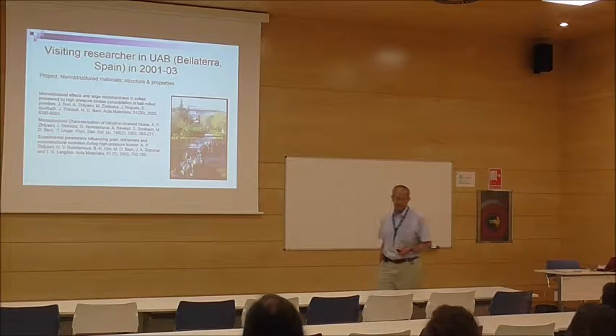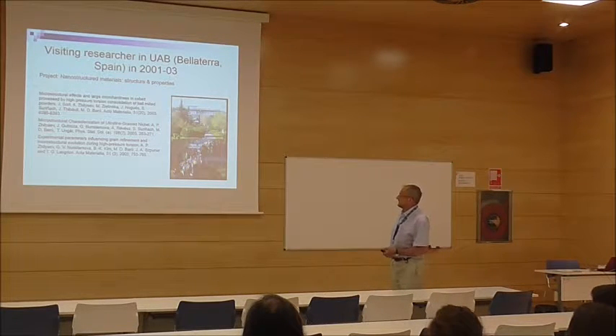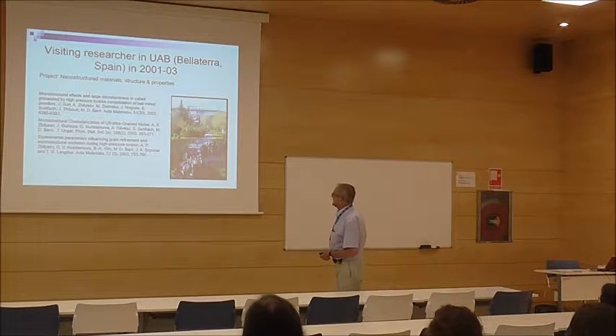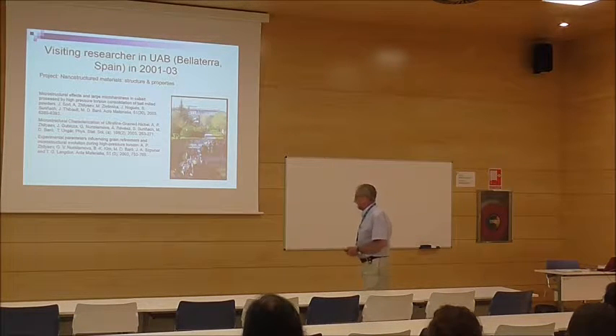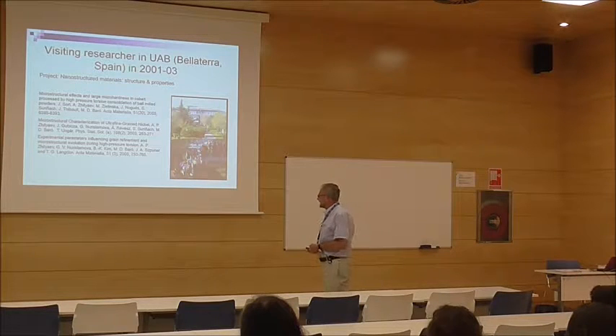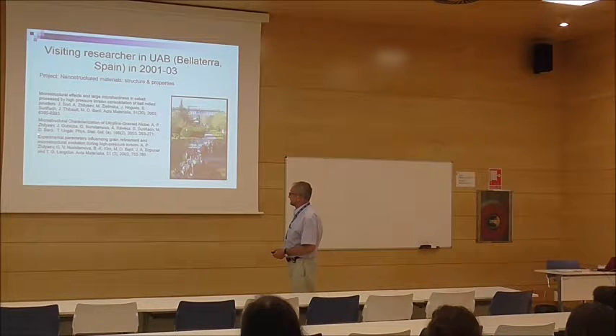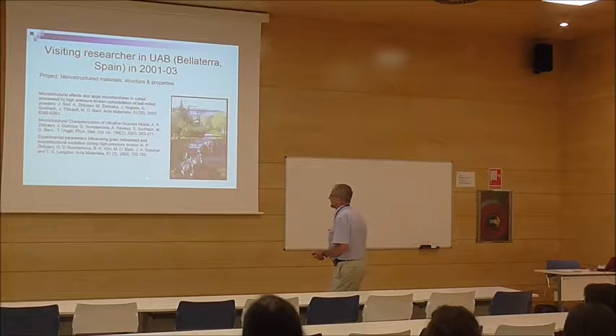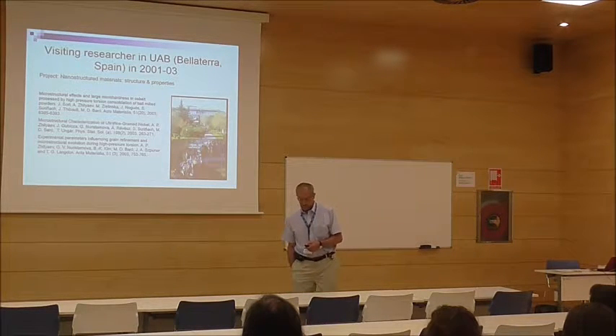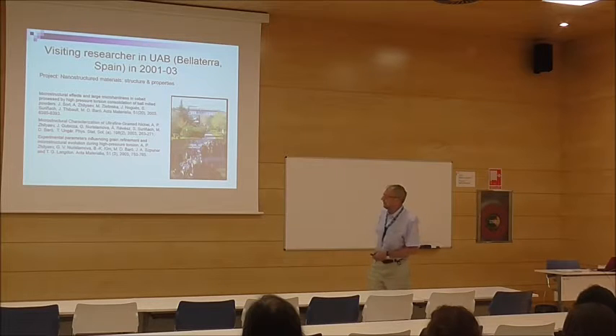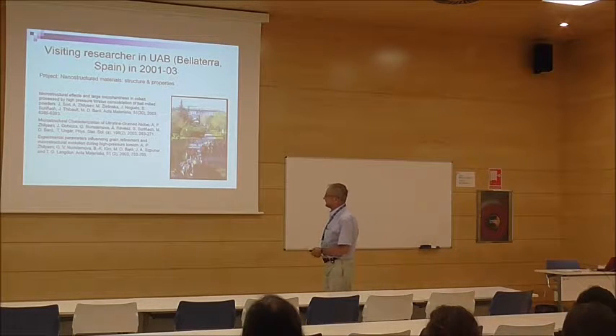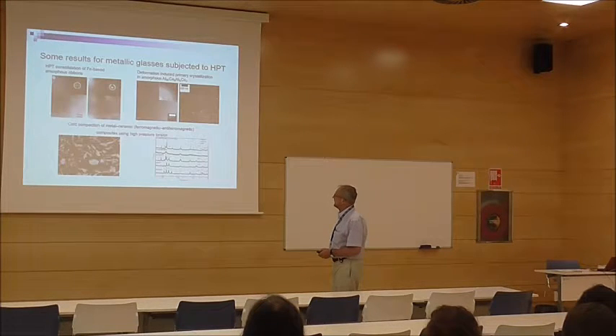So this is Spain. This might be last Spain because I'm here the third time. The first time it was at Bellaterra near Barcelona, the Universidad Autónoma de Barcelona, and I lived in Cerdanyola, a very nice small village. So we did some work, especially on experimental parameters influencing grain refinement, published in Acta 2003, which has more than 500 citations now. So this is a research paper, not a review, because a review gets citations much more easily.